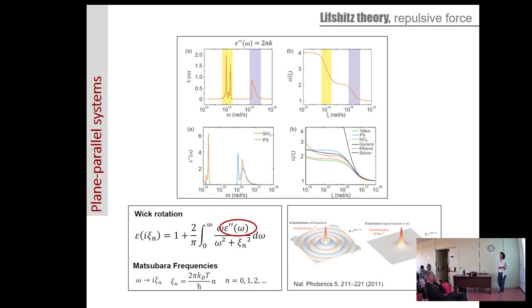The thing is that once we play with this rotation, any kind of intuition we can have about the material due to their optical properties is somehow lost, because here I'm showing you the imaginary part of the refractive index as a function of the frequency, and here is the transformation to Matsubara frequencies. So anytime we have an absorption, there's going to be an increment of the slope in this curve, and anytime we have a transparency, we have a flat band here. So we are going to check that in the equation that I showed you before in this kind of plot, especially for our design.